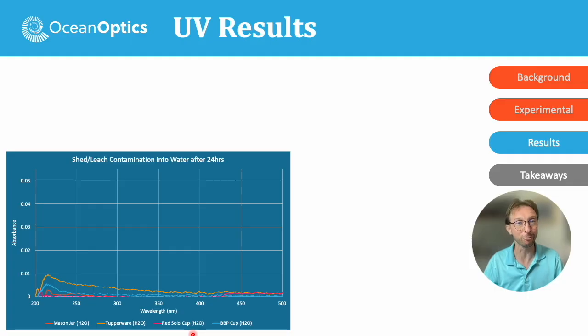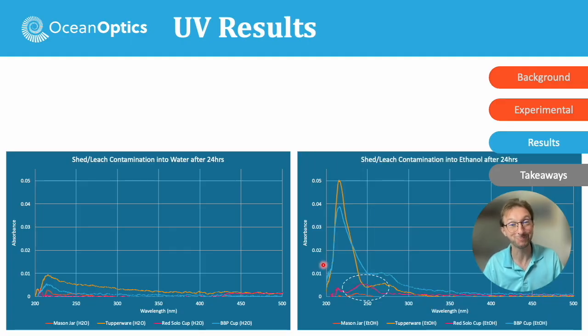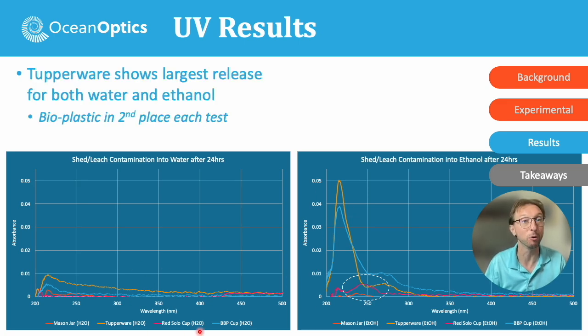But check out ethanol. Look at this. It's a night and day difference, as you would expect, right? So this is a solvent that's pulling out much more of those chemicals at a higher rate. And it's about 5 times increase. So this is just above 0.05, and this is just below 0.01. So it's an over 5x increase for both the Tupperware and the bioplastic.